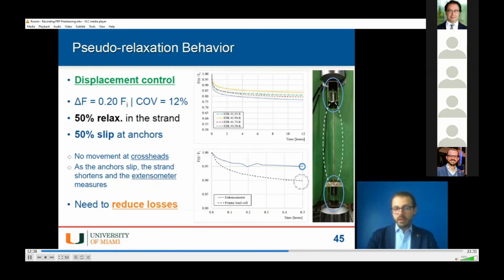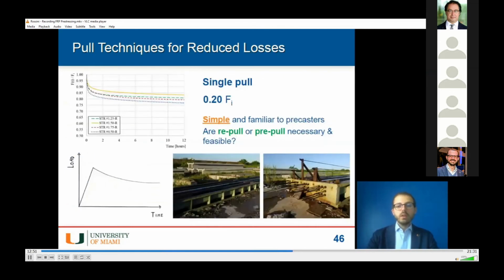Now, this level of losses, 20%, even though on a short length, was deemed excessive to achieve effective pre-stressing on site, and so we decided to try alternative pulling procedures to make it feasible and more efficient. In trying different alternative procedures, you should keep in mind that sometimes you deal with very refined pre-stressing facilities, sometimes you are just in the jungle, as you see from the picture there, and that's a very typical pre-tension yard in South Florida.